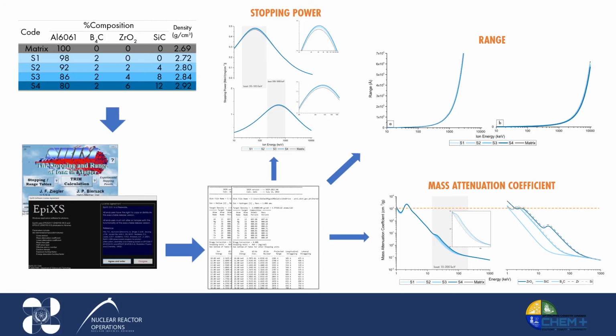Likewise, the peak occurred between 15 and 200 keV where the value of MAC is increasing with the increasing content of zirconium oxide and silicon carbide. At the same energy range, there is a peak brought about by the zirconium oxide component. It is also compared with the MAC of zirconium and silicon. Still, zirconium has more peaks due to the higher Z value among the two elements.